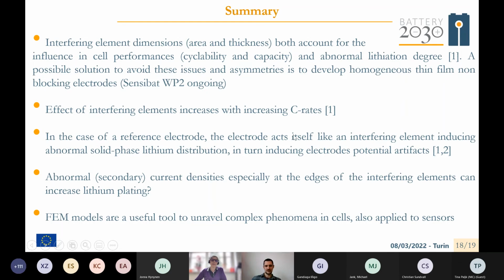Second point: the effect of interfering elements increases with increasing C-rates. In the case of a reference electrode, the electrode itself acts like an interfering element, introducing abnormal solid phase lithium distribution, and in turn inducing electrode potential artifacts. Abnormal and secondary current density, especially at the edges of the interfering elements, can increase lithium plating. Maybe there is a question point here, and FEM models are a useful tool to unravel complex phenomena in the cells, also if applied, for example in this case study, to sensors.